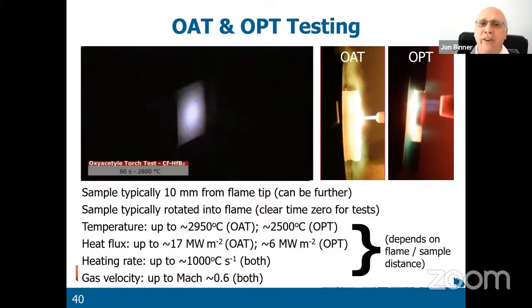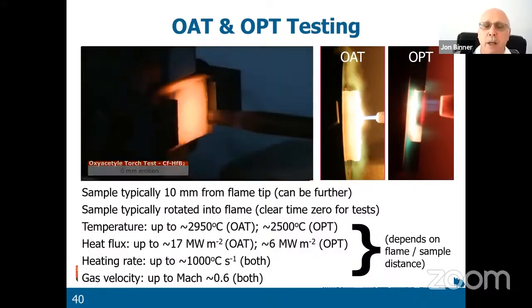We can then put a camera in, and we can actually watch what is happening to the surface of the sample during the test. Then we allow it to cool. This is the slowest part of the test. So we typically test materials for about 5 minutes. We'll just watch that again.